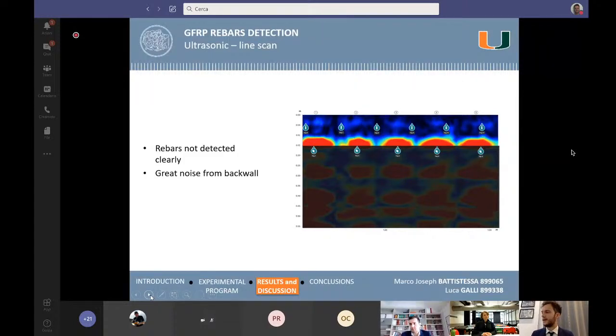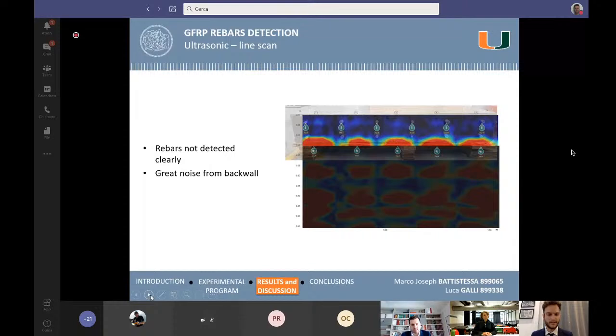Then, at the end of our experimental program, we performed a line scan with the ultrasonic test. And again, if we overlap the picture of the slab on it, generally we cannot really say where the rebars are. The tags that you can see there have been manually placed, but there is not a clear detection of all the reinforcement, and also there is a great noise from the backwall. So the preliminary test performed shows that the ultrasonic test seems to be not effective to locate this kind of reinforcement. Nevertheless, further tests with different types of concrete and also an on-field application are essential to evaluate the real effectiveness of the ultrasonic test.